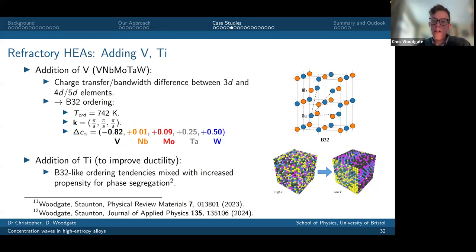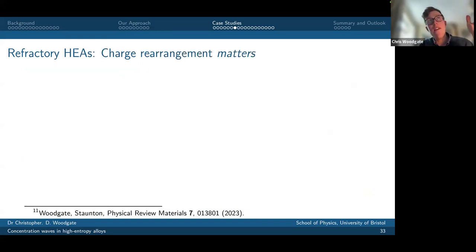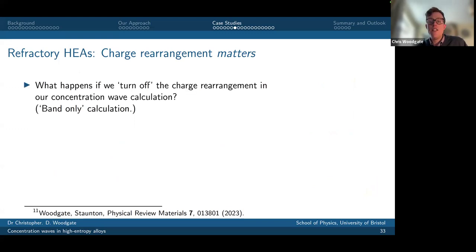And the other thing I wanted to highlight, because I think this is kind of more of a theoretical seminar, is that, okay, this charge rearrangement that I've been mentioning, and I highlighted at the start, the S2 theory is properly accounting for the charge rearrangement. It turns out that really matters in a lot of these systems. So we can ask the question, what happens if we turn off the charge rearrangement in our calculation? Because the way the theory is constructed, we can do that. We can do what we call a band-only calculation.